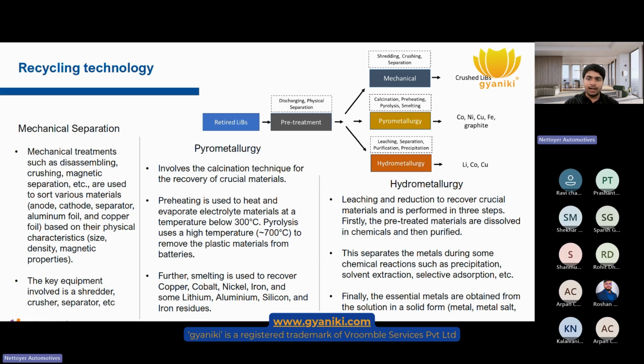Secondly, we'll go with hydrometallurgy. The name itself conveys that in this process, we involve the usage of a lot of chemicals in order to extract the end material. With hydrometallurgy, we have one active material, the black mass. Now, this black mass is treated with the help of a chemical process. We chemically wash the complete black mass, and then we get the lithium metal salt, lithium carbonate. We have the precipitation process, the deposition process, and then the solvent extraction and adsorption process as well. So there are three different processes involved in hydrometallurgy.